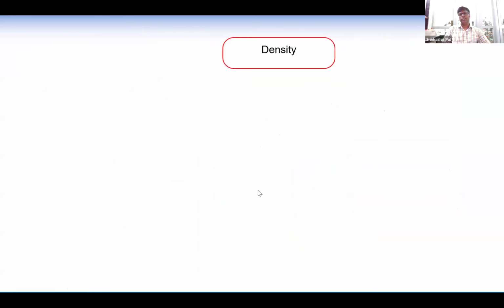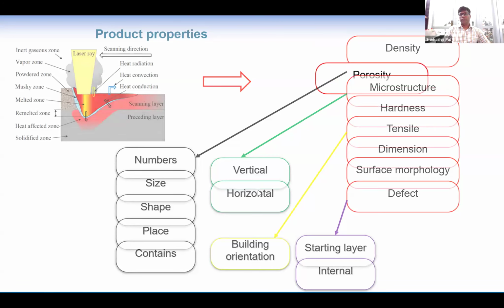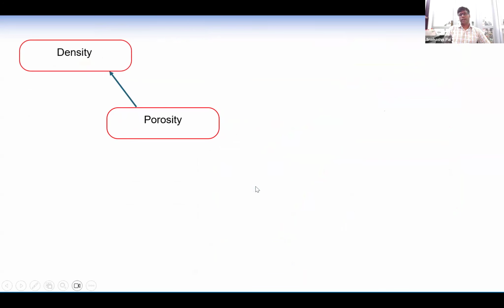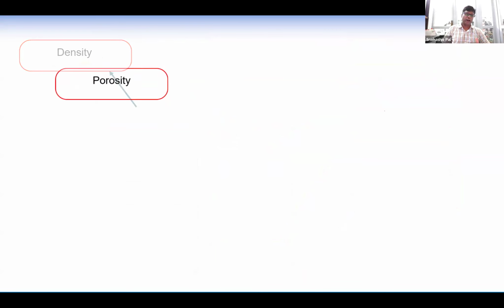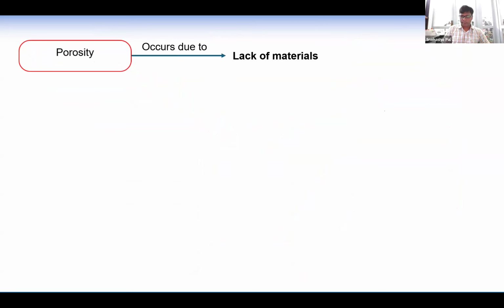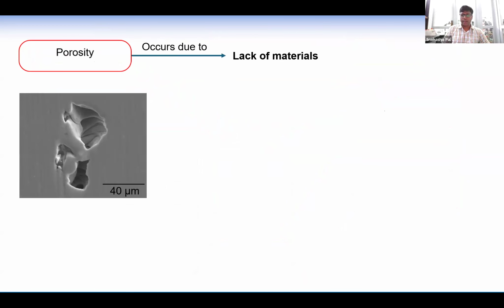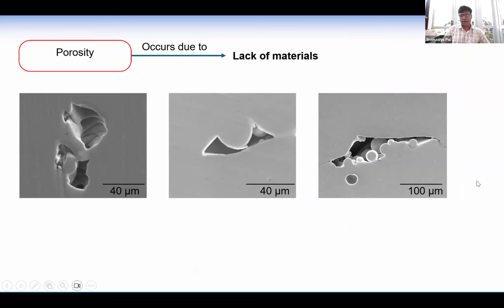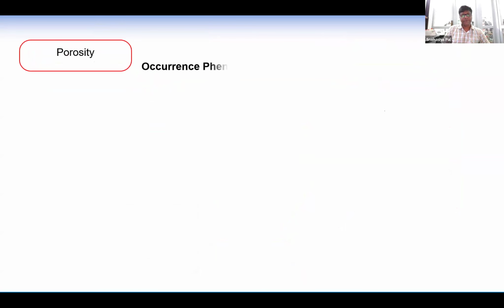Density mostly depends upon the porosity. If we can minimize the porosity, density will be enhanced. Why does the porosity occur here? Because of the lack of material, obviously, and it looks mostly like this. I will explain this in a little more detail later. The phenomena are mostly material sputtering, where molten metal can sputter out from the action zone.